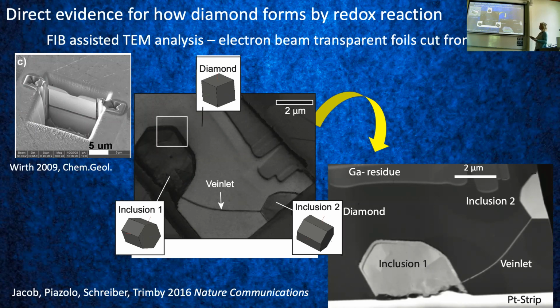Using FIB-assisted TEM analysis, we were cutting foils through this one diamond, and that was really, between you and me, luck. We cut about 50 foils, and one of them happened to have these beautiful inclusions. We had one inclusion here, one inclusion there, connected with this little veinlet in this foil, which was otherwise just diamond. The material up here is just gallium precipitate from the gallium ion beam, so that's an artifact. But the rest here is diamond, and it has these two inclusions.